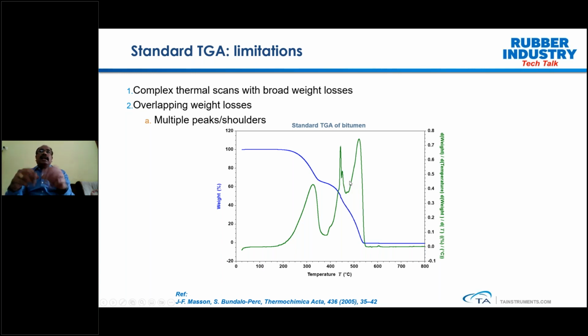and also it is overlapping. So when you do the composition analysis, you should know the onset of decomposition and the endset, so that you can easily calculate the associated weight loss. But in this case, since the transitions are overlapping, it is a bit difficult to easily calculate when exactly the decomposition is starting. On many occasions, we may have this kind of challenge when running TGA samples.